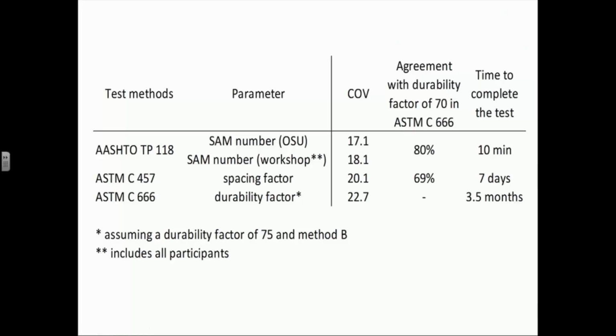If you compare the coefficient of variation for what's reported by ASTM C457 for the spacing factor, that's a coefficient of variation of 20.1%. And if you look at the coefficient of variation for what's reported for a durability factor of about 75, using method B, you get a coefficient of variation of about 22.7%. They're all very, very similar to one another. Yet, the super air meters only take 10 minutes versus 7 days or 3.5 months. The super air meters have an 80% agreement with the freeze-thaw test, and only a 69% agreement with the spacing factor.